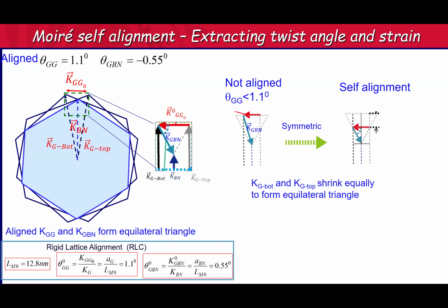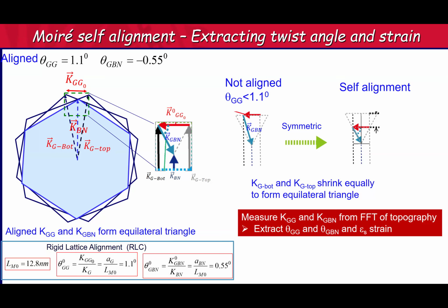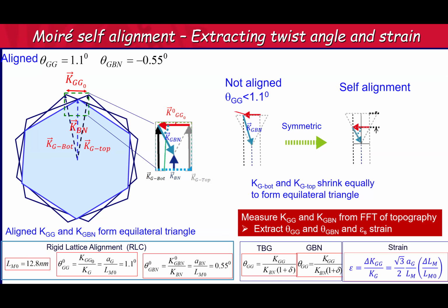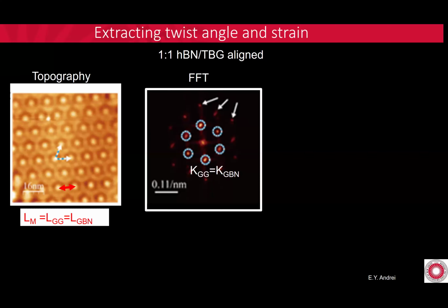And now if you have strain, let's give one example of strain. Let's say that theta GG is a little less than 1, so these two graphene wave vectors are going to be closer to each other. So the system is going to relax in order to create alignment, because that lowers the energy, like this. Basically graphene is going to stretch, and so these lines are going to get shorter, and you get alignment. We can exactly calculate the final KGG and KGBN from the FFT of the topography, and we can extract the two twist angles, which we don't know a priori, and we can extract the strain, and here are the formulas. I'm not going to bore you with the formulas. So let me give you an example here.